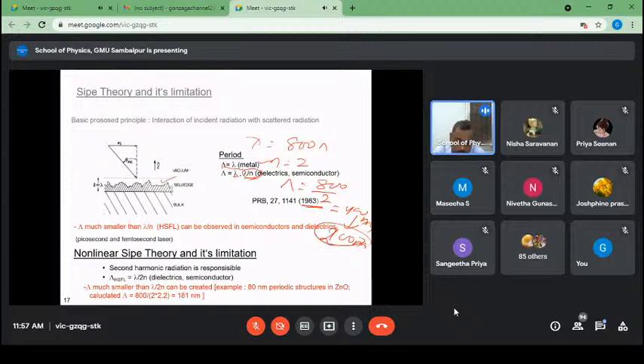So we have proposed that second harmonic radiation is responsible for this. As soon as light falls on such a rough surface, second harmonic generation can take place. Second harmonic generation is a phenomenon by which, when a laser beam falls onto materials, its frequency is doubled and wavelength is halved. So this is called the second harmonic process. When lambda becomes lambda by 2, the periodicity will be much smaller than lambda by n, and this fits much better.